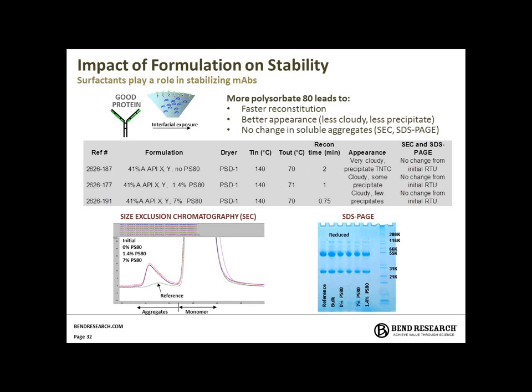This was a proof of concept study. We realized these Tween conditions were fairly high. This was simply a proof of concept program to look at, can we do this? Can we actually modify mAb quality using formulation and process? And as we've shown, we saw an increased resuspension rate with the higher Tween contents and a decrease in precipitates using surfactants like Tween. Since this program, we've been looking at lower levels of Tween to impact particle quality and resuspension rates themselves. It's an ongoing effort.